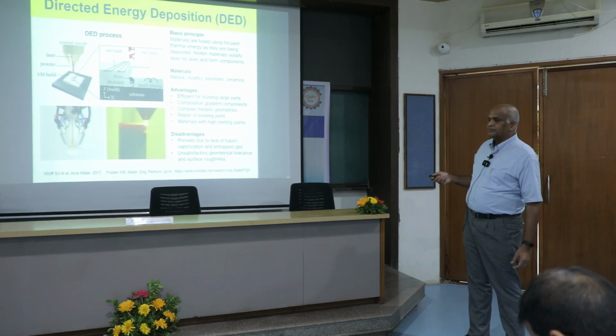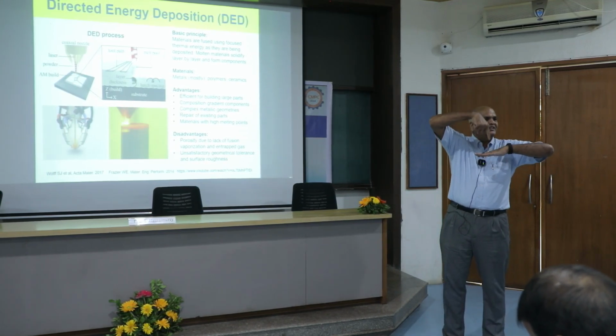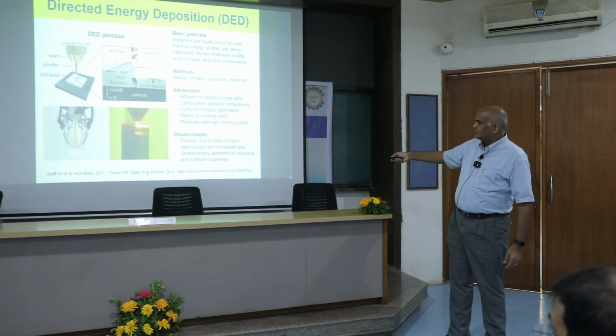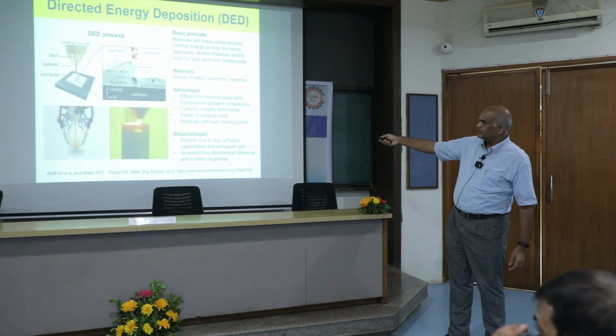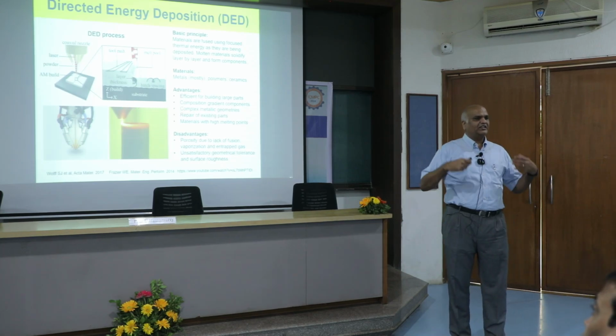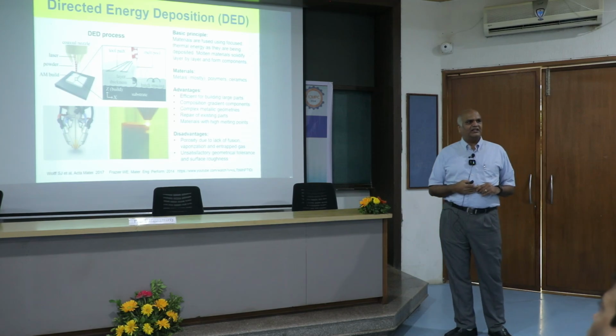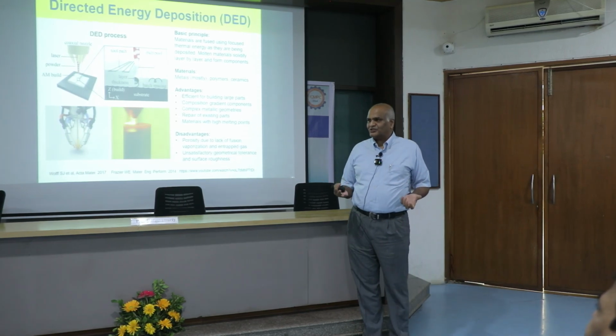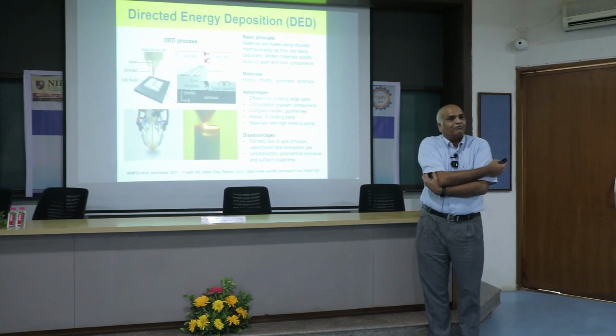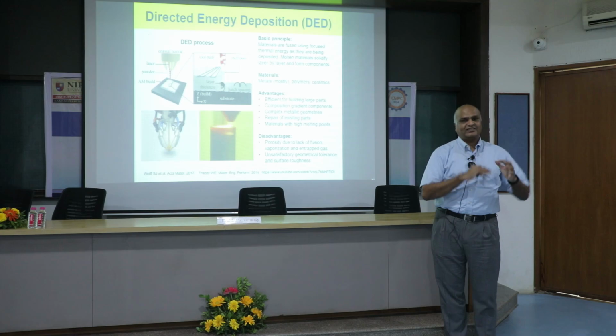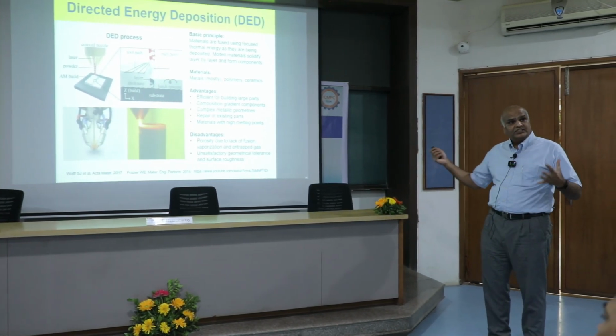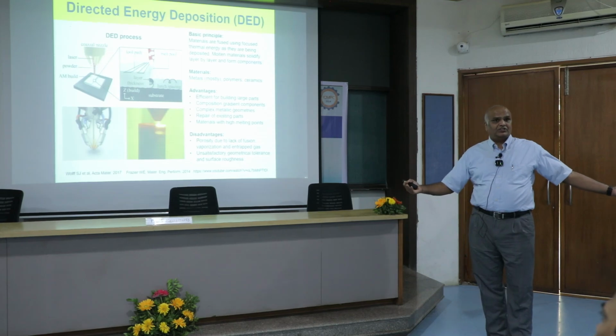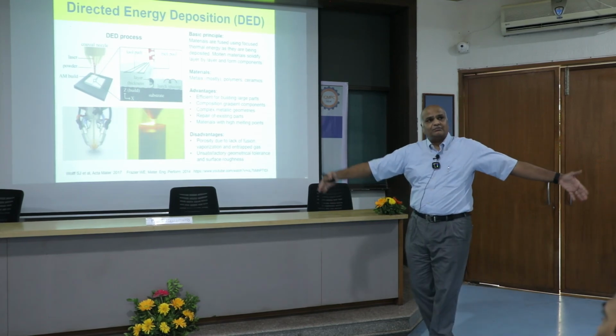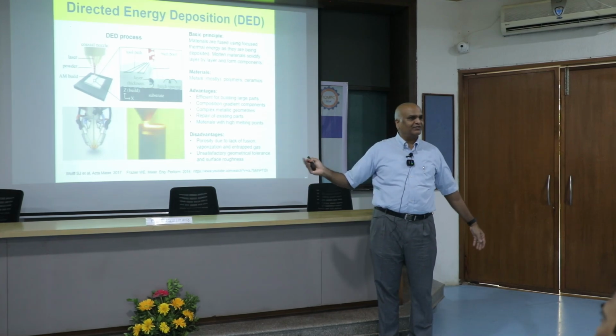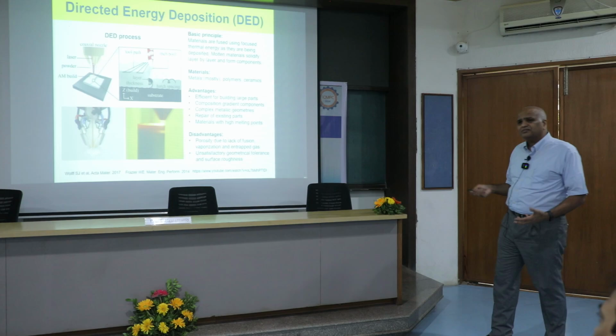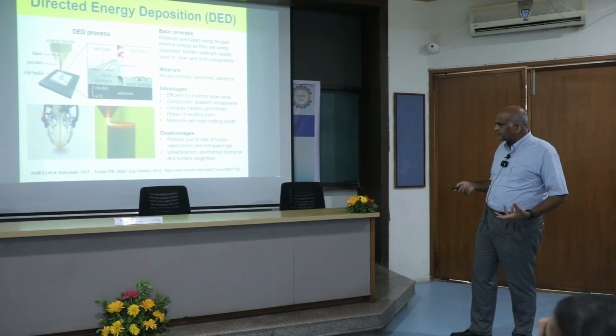In directed energy deposition, this is a lot more common, simpler thing. What you do is basically you have a CNC machine, and instead of the machine tool, you put a laser beam. And what happens is, coaxially, you can see it here, the laser comes and the powder also comes, and in flight the powder melts and gets deposited. You have 5 degrees of freedom that is possible with CNC machines. As a result, you can have much more complicated structures built with this. You can rotate it in the 5 degrees of freedom. So this one allows you to build very large parts. There is actually a California company which builds whole rocket casings in one shot with this technique. But it's much coarser, and there are a lot of differences with this technique.